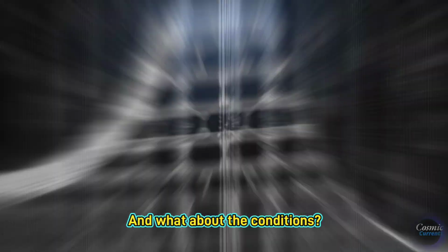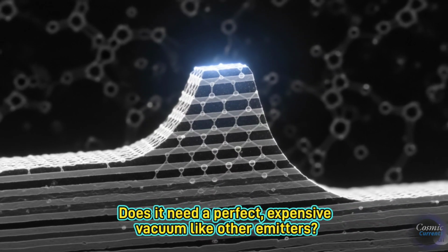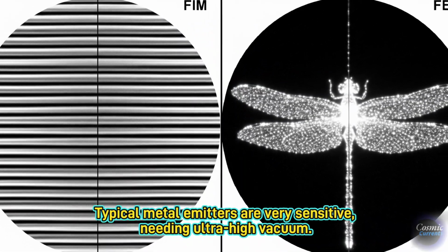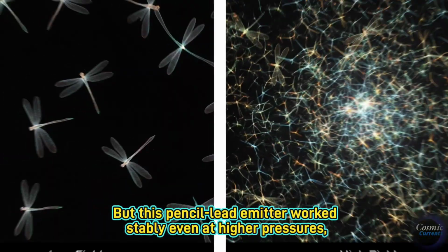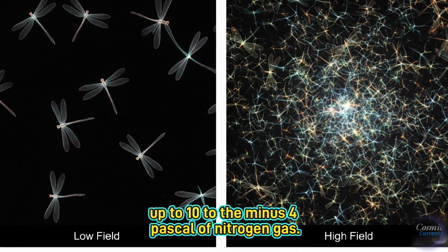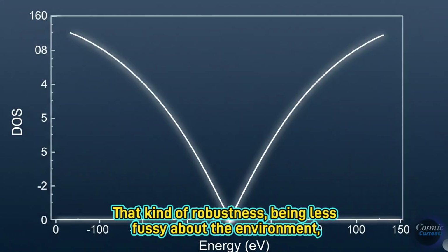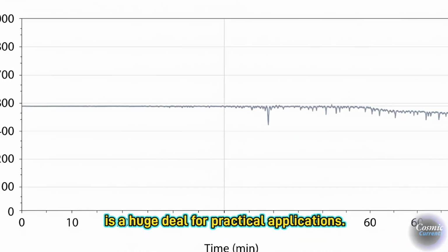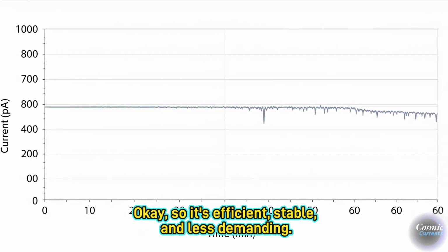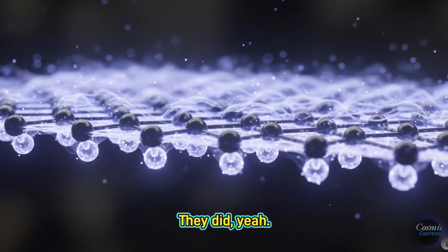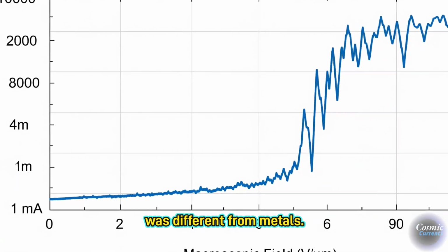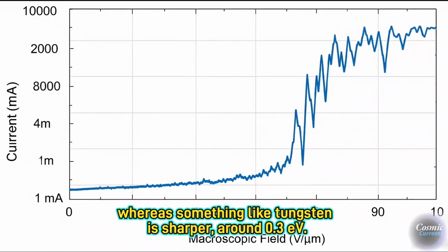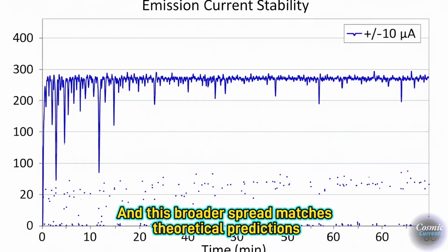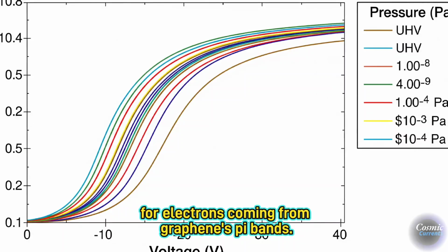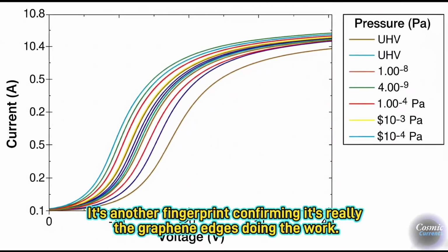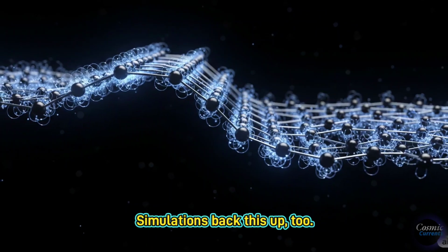That's really stable performance. And what about the conditions? Does it need a perfect, expensive vacuum like other emitters? That's a key advantage. Typical metal emitters are very sensitive, needing ultra-high vacuum. But this pencil lead emitter worked stably even at higher pressures, up to 10 to the -4 Pascal of nitrogen gas. That kind of robustness, being less fussy about the environment, is a huge deal for practical applications. Okay, so it's efficient, stable, and less demanding. Did the electrons themselves tell them anything special? They did, yeah. The energy spread, the spectrum of the electrons coming off, was different from metals. It was broader, about 0.7 electron volts, whereas something like tungsten is sharper, around 0.3 eV. And this broader spread matches theoretical predictions for electrons coming from graphene's pi bands. It's another fingerprint confirming it's really the graphene edges doing the work. Simulations back this up too.